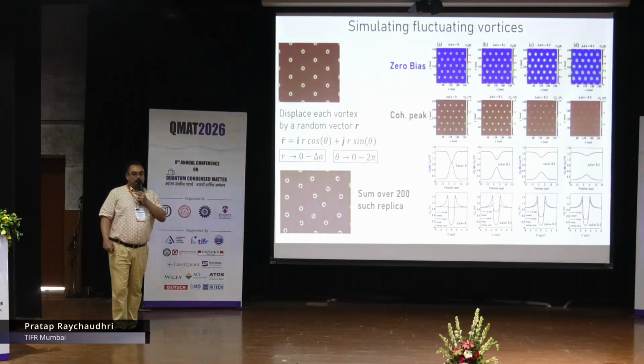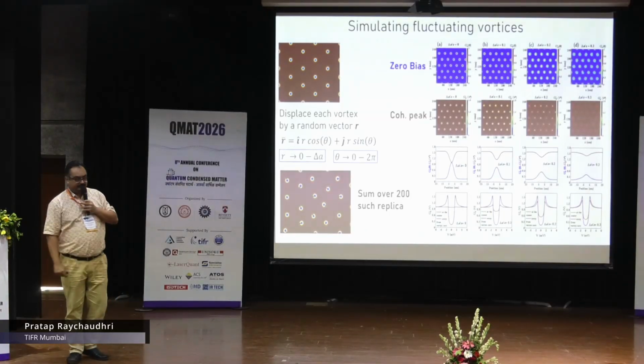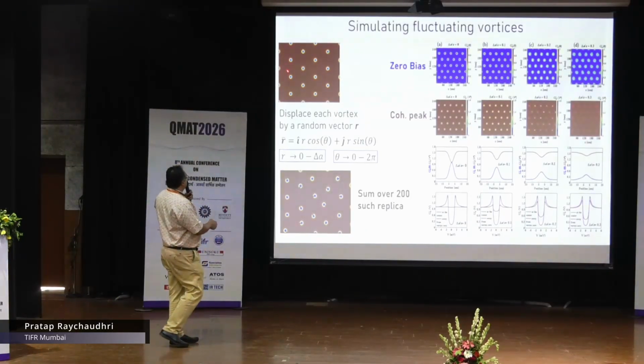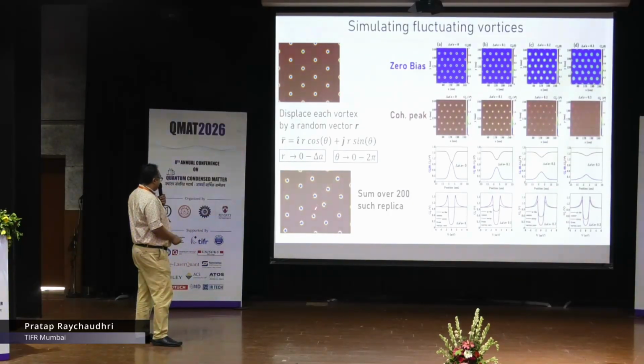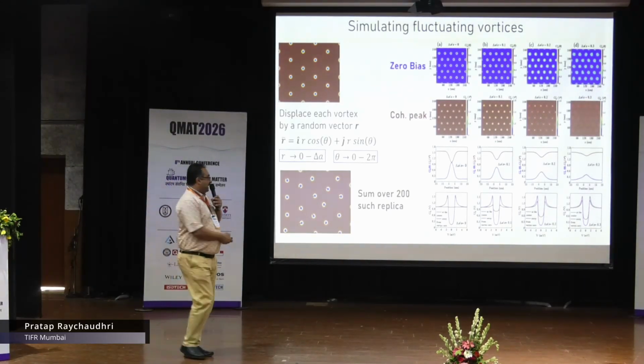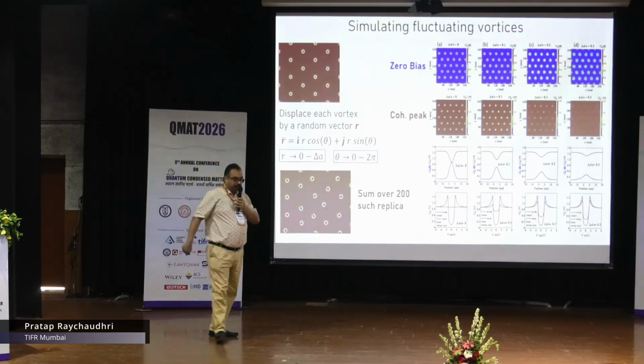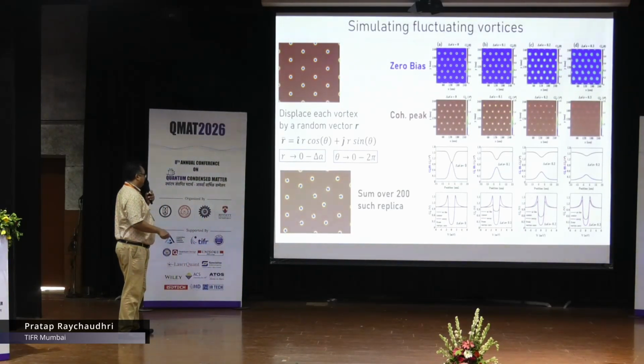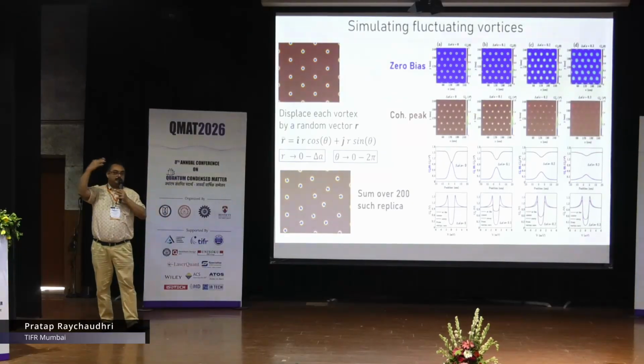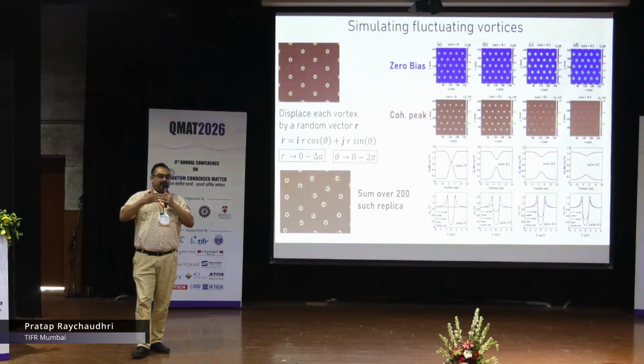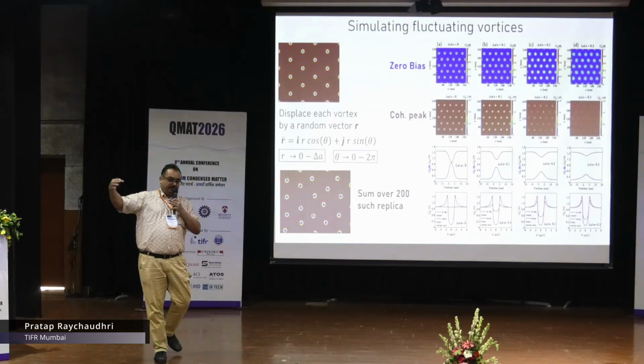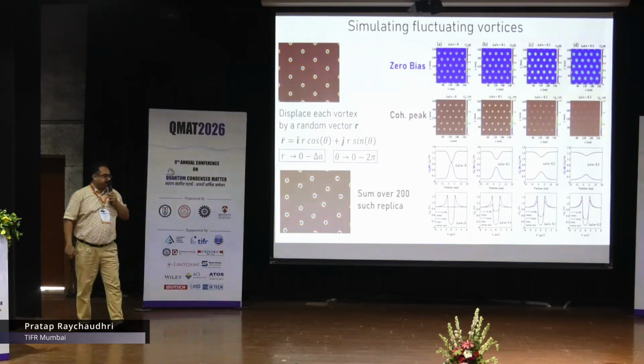Now, in order to simulate the shaking vortex, we take this perfect vortex lattice and displace each vortex by a vector r, where the magnitude of r is a random number between 0 and a maximum value delta A, and the angle is also a random number between 0 and 2 pi. With this protocol, we create 200 replicas and sum over them. So this is in effect ignoring retardation effects. So we have somewhat of a Born-Oppenheimer approximation.